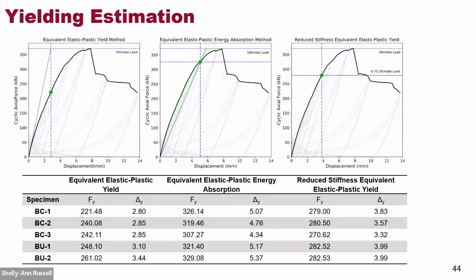The yielding point of specimens was estimated using 3 methods. The first was the equivalent elastoplastic yield method. So by drawing this first stiffness to that ultimate point, we found this point. And also by equalizing these two areas, it's called the energy absorption method. And we have this reduced stiffness by 25%, and this point is called the yielding point. So among these 3 methods, the reduced stiffness method was near to our theoretical calculations. As you can see, all are near to 4 mm.